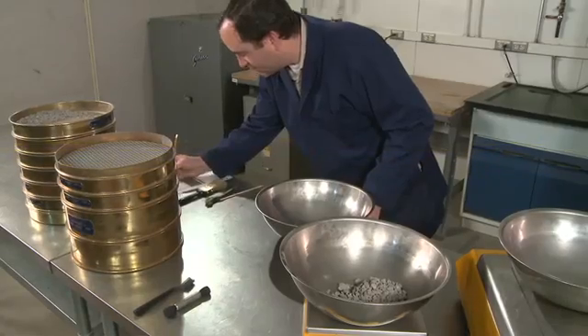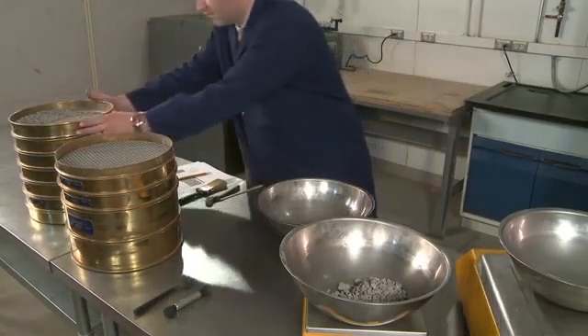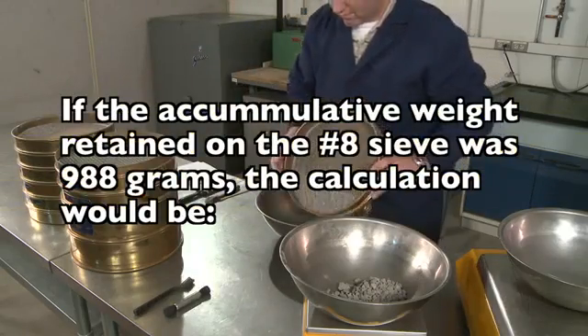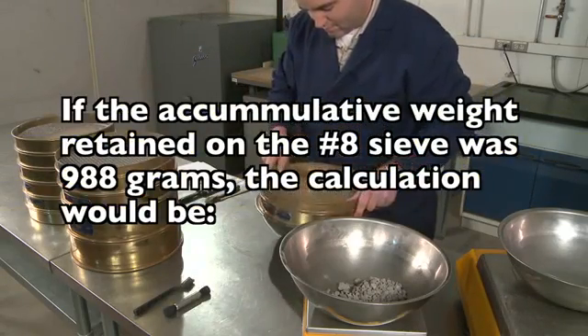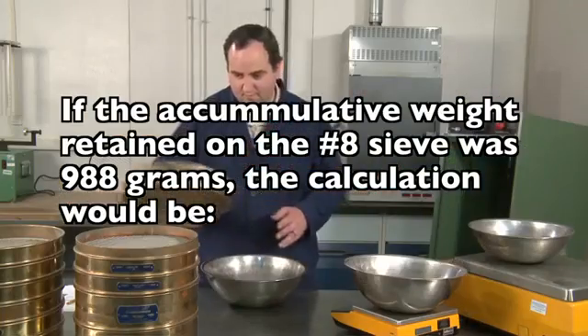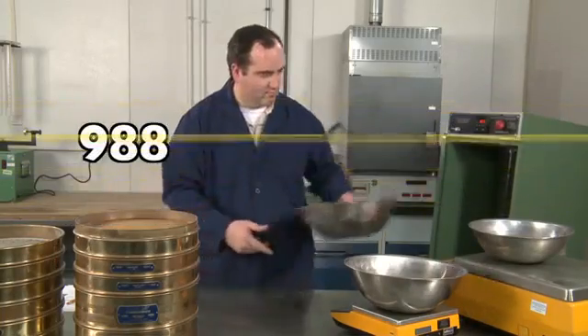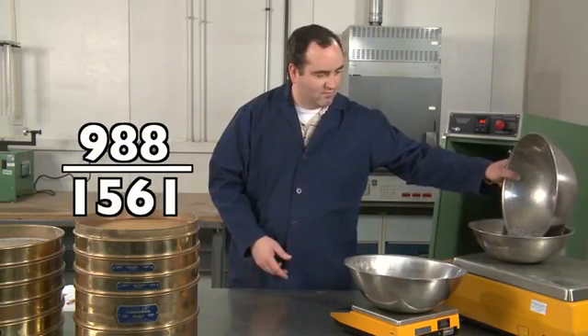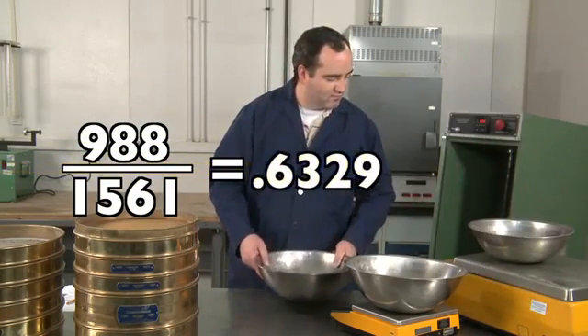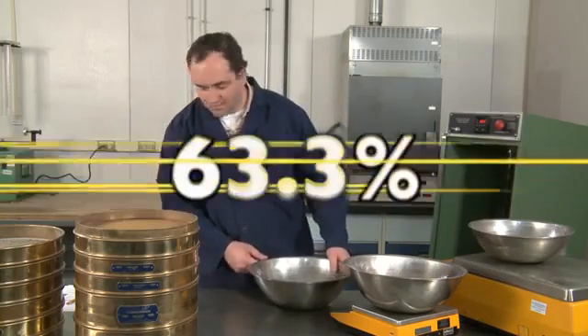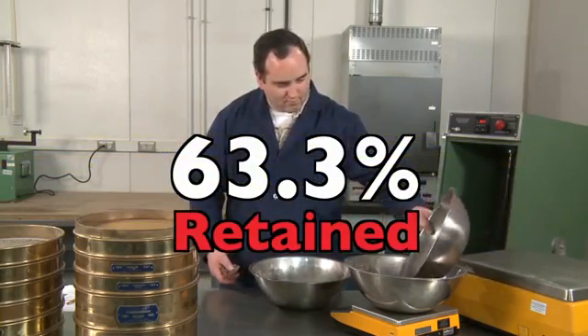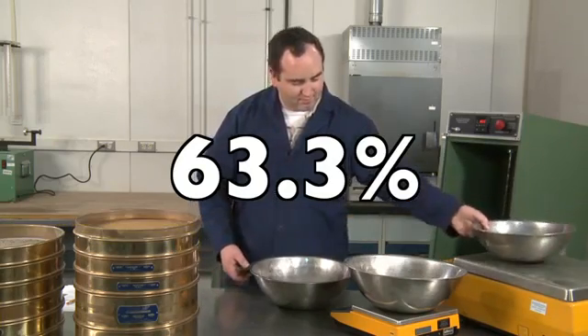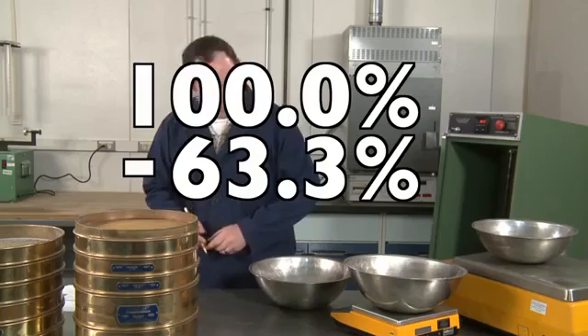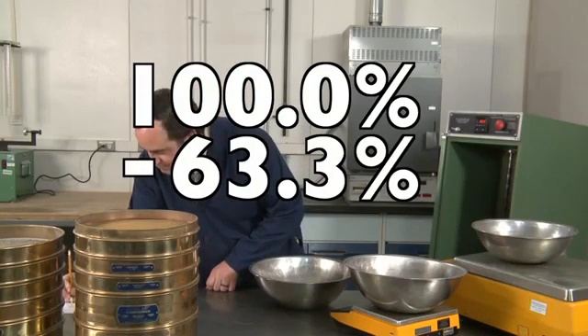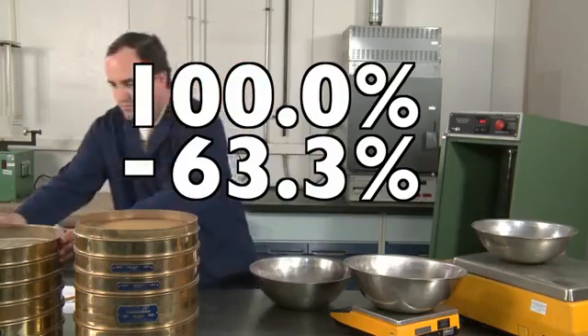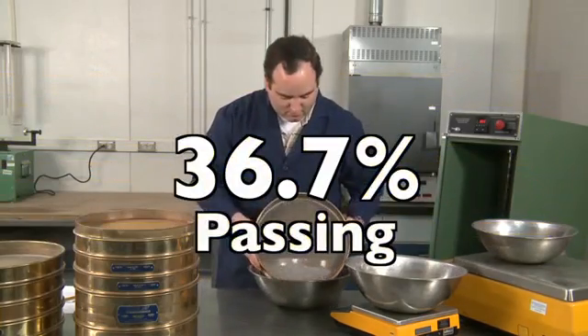A more common calculation would be the total percentage passing each sieve. So, if the accumulative weight retained on the number 8 sieve was 988 grams, the calculation would be 988 divided by 1561 equals 0.6329 times 100 equals 63.3% retained. Simply subtract the percent retained from 100 to obtain the percent passing the number 8 sieve. 100 minus 63.3 equals 36.7%.